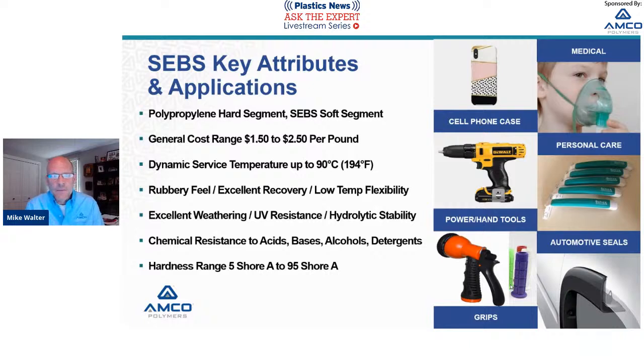The first is a SEBS. It's a styrene ethylene butylene styrene. Its key attributes and applications are as follows. First and foremost, a SEBS is made with a polypropylene hard segment and a SEBS synthetic rubber soft segment. The general cost range for SEBS type elastomers is $1.50 to $2.50 a pound. They have a dynamic service temperature of up to about 90 degrees C or 194 F.